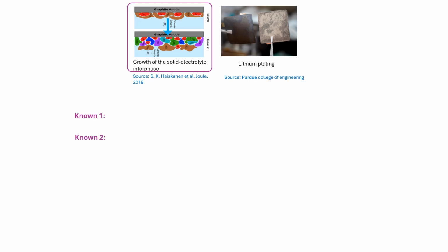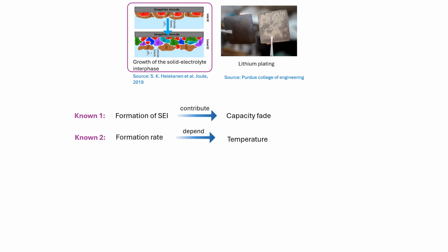There are 2 known facts for this modeling method. The first one is that the formation of SEI contributes to the capacity fade of the battery. Another one is that the formation rate depends on the temperature. Based on the known facts, we can develop 2 analytical models. The first model is a mapping between the amount of SEI formation and the capacity fade of the battery. And the second model uses the Arrhenius equation to fit the formation rate and the temperature.